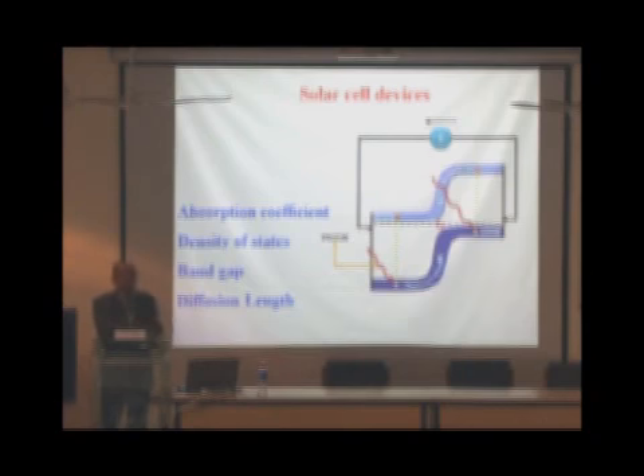The efficiency of a solar cell depends on these parameters: absorption coefficient, density of states, band gap, and diffusion length. What I wanted to show you was that some of these parameters we can control by controlling the dimension of the nanomaterial. So if we form a solar cell using nanoparticles and nanorods, it is possible to change the band gap of the semiconductor material and hence change the wavelength at which the solar cell will work efficiently.